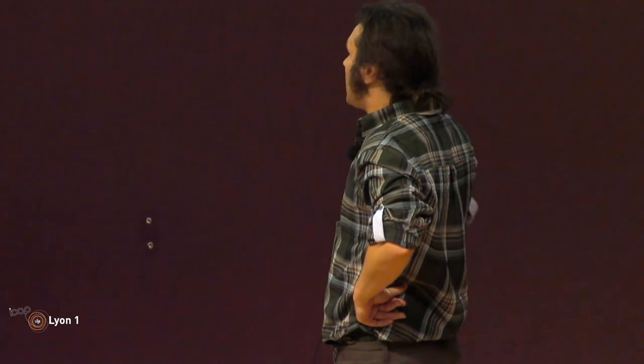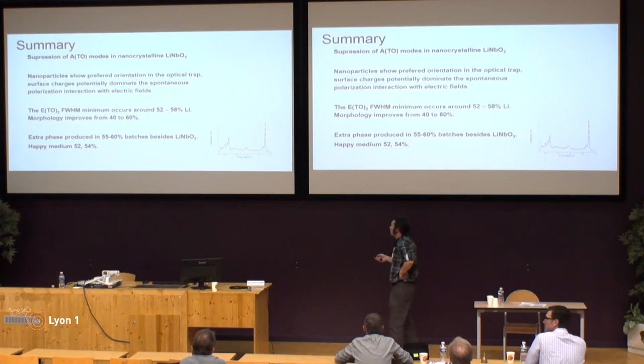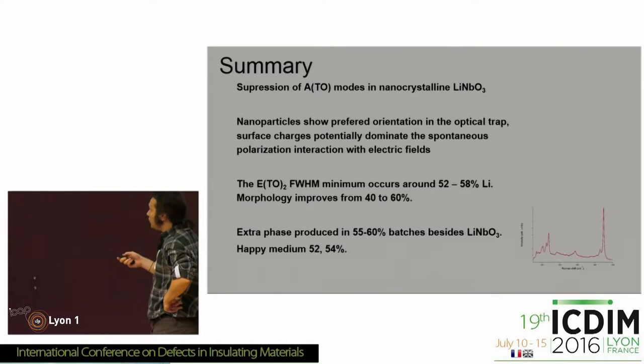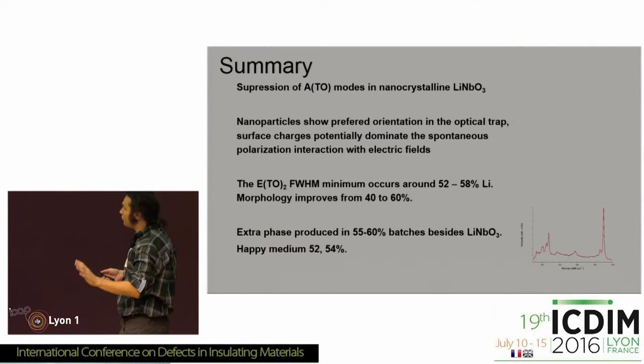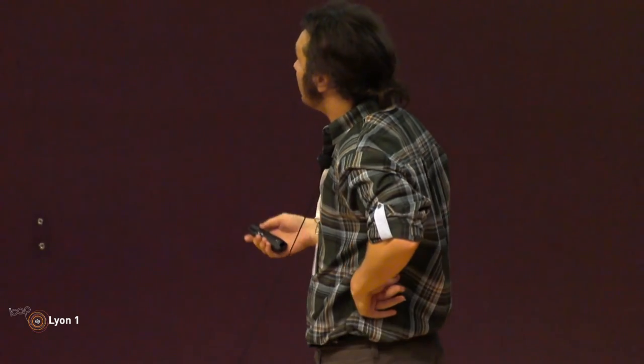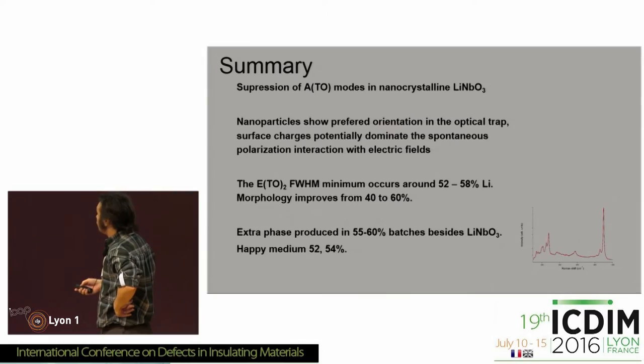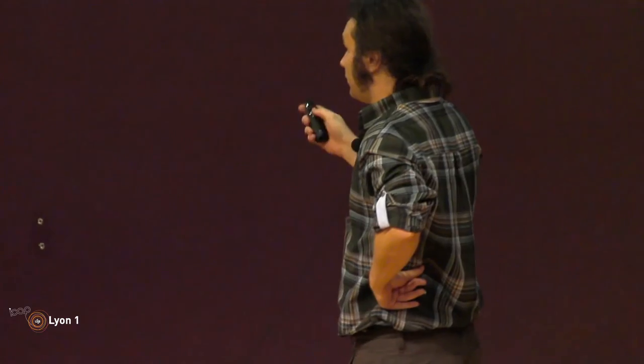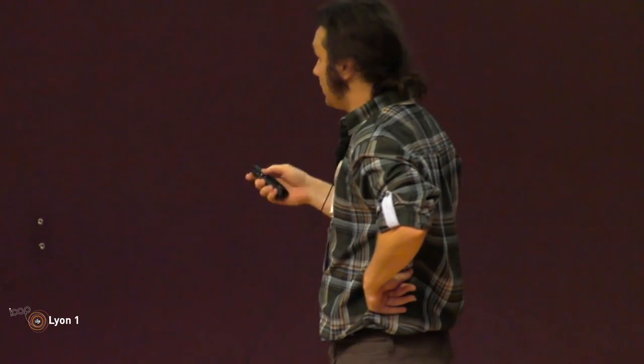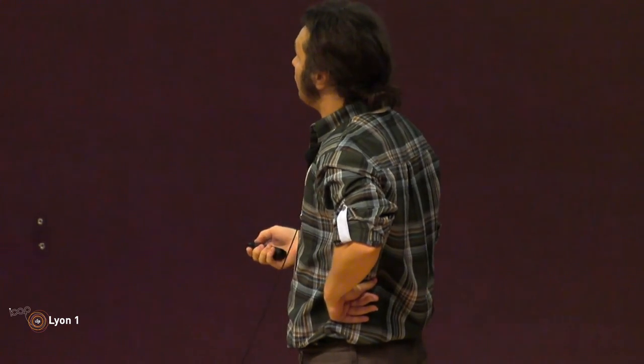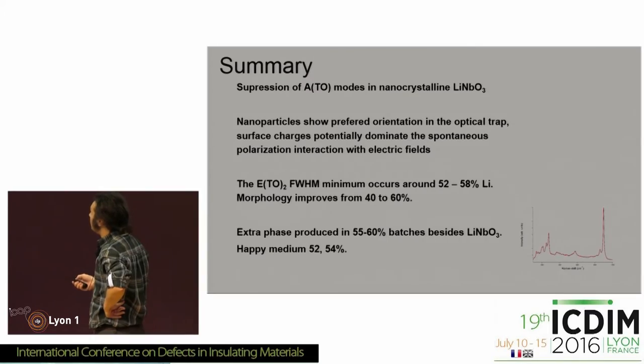In certain batches you get an extra phase. As I said, it was the lithium-rich side where you notice this, and it turns out to be a lithium-poor phase. To balance all of these things: you don't want nanocrystals from the lithium-poor batches because they don't come out very well, as the microscope images showed. And you also don't want the presence of this extra centrosymmetric phase. So it seems like to get stoichiometric spherical nanocrystals, there's kind of a happy medium around 52–55 percent. And that's my talk.